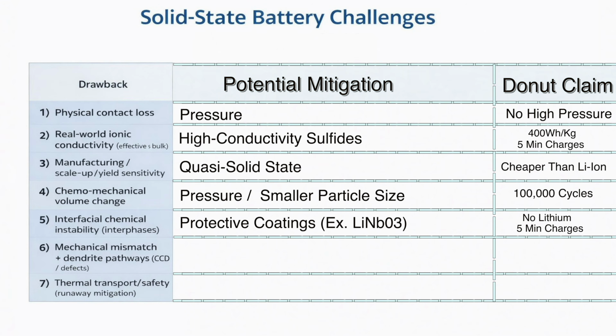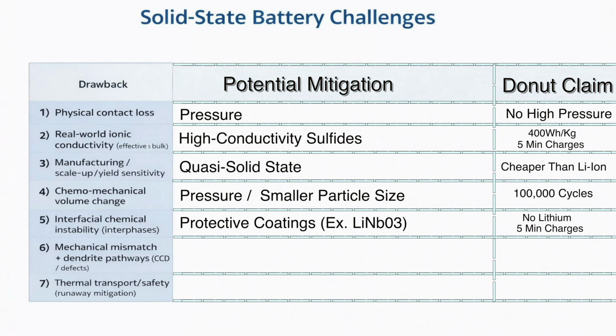Mechanical mismatches are one of the causes of dendrites. Mismatches create defects and failure hotspots over time. Add enough current, and even so-called dendrite-blocking ceramics fail. A common mitigation here is, again, pressure. Donut claims 100,000 cycles and no dendrite growth.